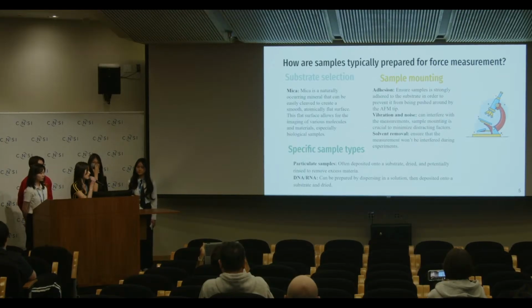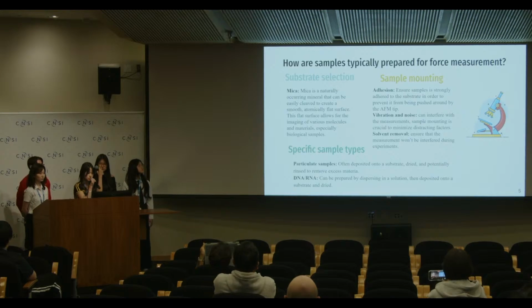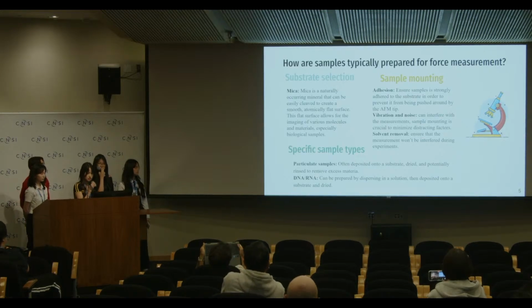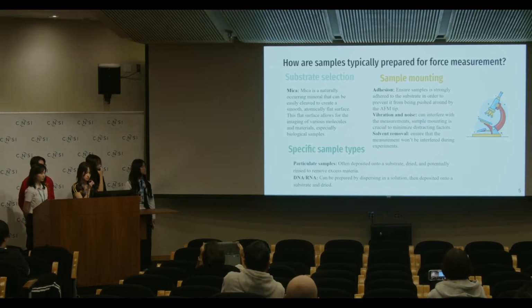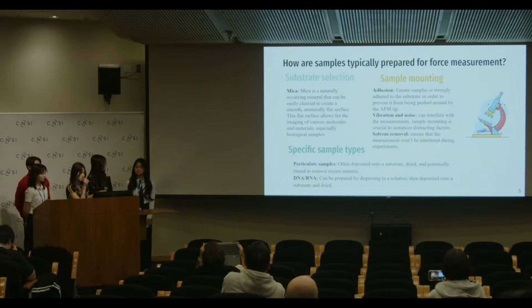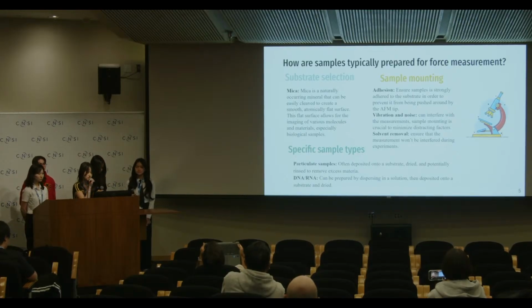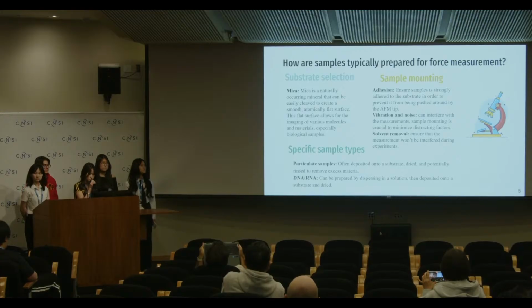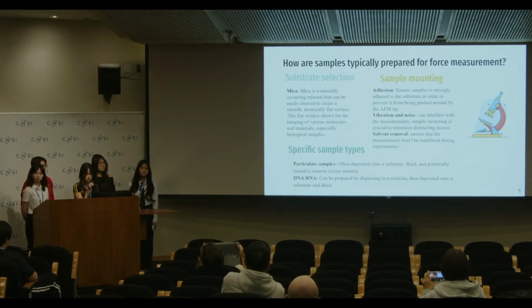Okay, so how are samples typically prepared for force measurement? Number one, we have substrate selection. The most commonly used substrate for AFM is called mica. Mica is a naturally occurring mineral that can be easily cleaved to create a smooth, atomically flat surface. This flat surface allows for the imaging of various molecules and materials, especially biological samples.